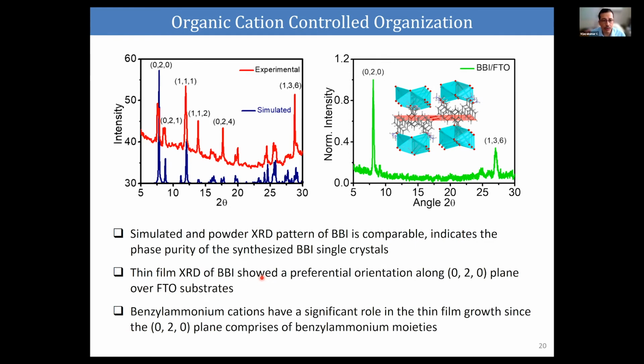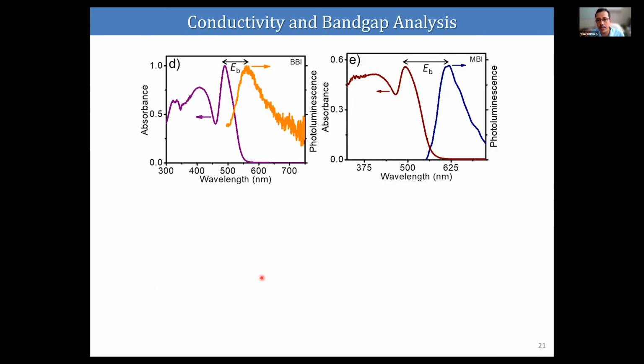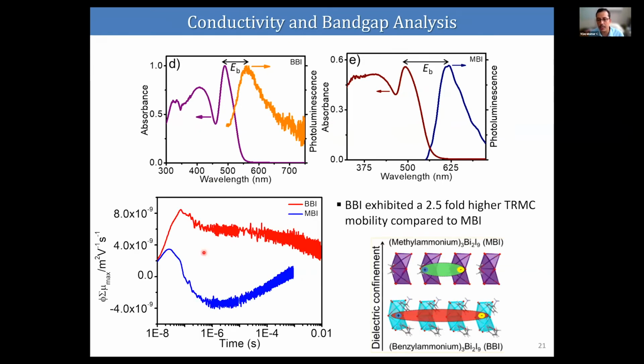And we found that in our material, the exciton binding energy is much lower than the standard material. And because of that, our material showed a 2.5-fold enhancement in the microwave conductivity. So that is basically the intrinsic conductivity of the material measured in the nanometer scale. So our material is showing very good conductivity compared to the methyl ammonium, the standard material.